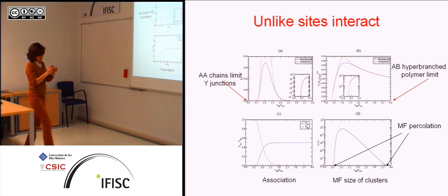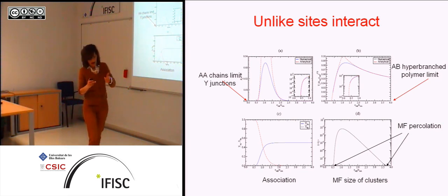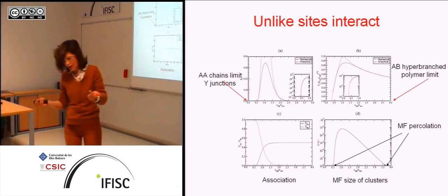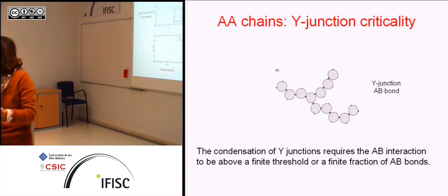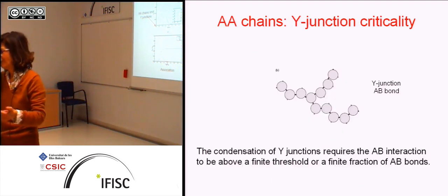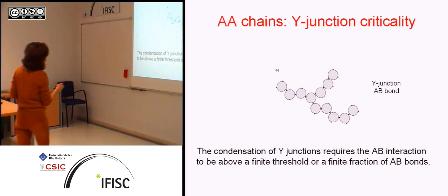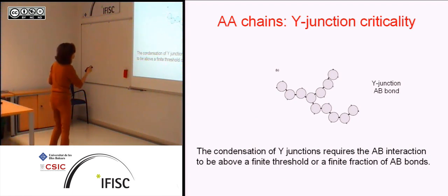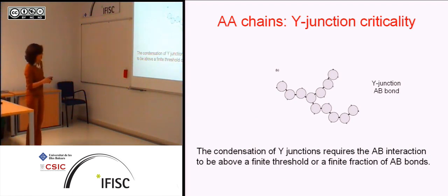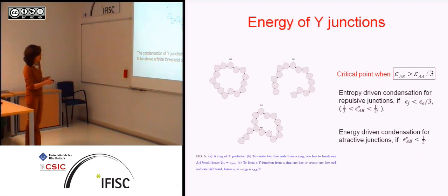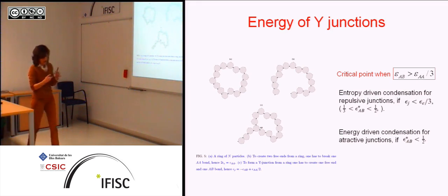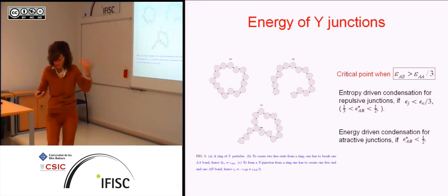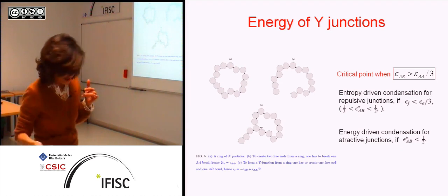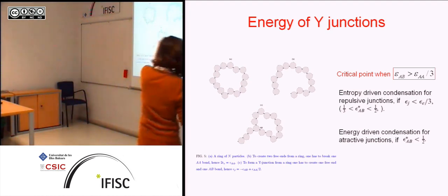So if we start from zero and switch on the AB attractions, these A chains will not condense until a finite fraction of AB junctions occur. And so this is a Y junction. This condensation requires a finite threshold, or a finite fraction of bonds. This is interesting because it actually makes a connection with dipolar fluids and with a very elegant paper by Safran in Science that appeared in 2000.